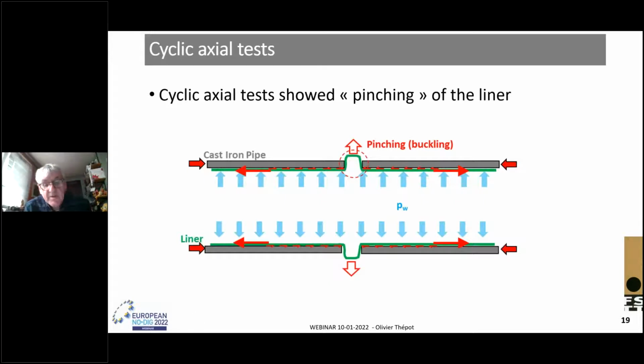Cyclic tests have revealed an important failure mode, which is pinching of the liner during the dynamic closing of the gap. Pinching arises for gap openings greater than 12 millimeters. The closing of the gap reverses the frictional forces, which can cancel the tensile force due to elongation and even create compressive force in the gap area. Compressive forces combined with internal pressure lead to buckling of the liner in the gap area. Repeated pinching damages the liner and reduces its tensile capacity after several cycles.